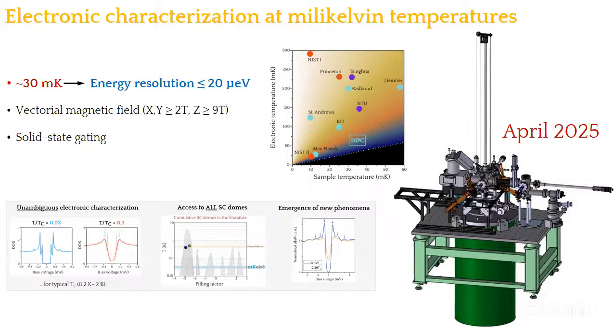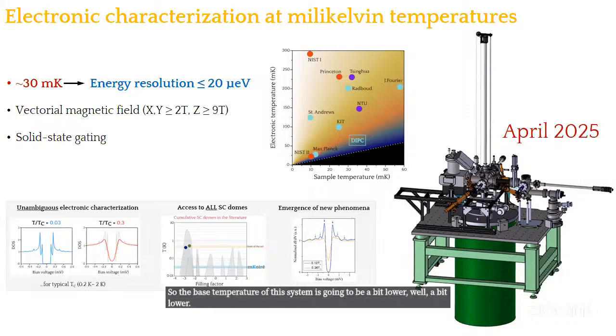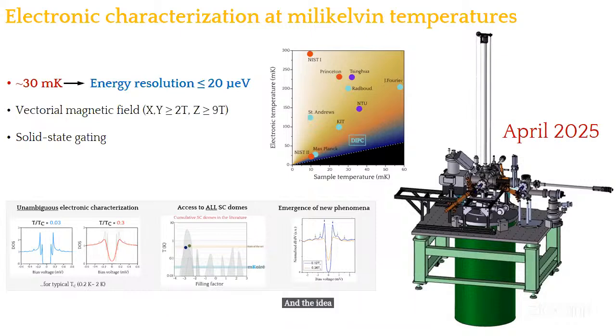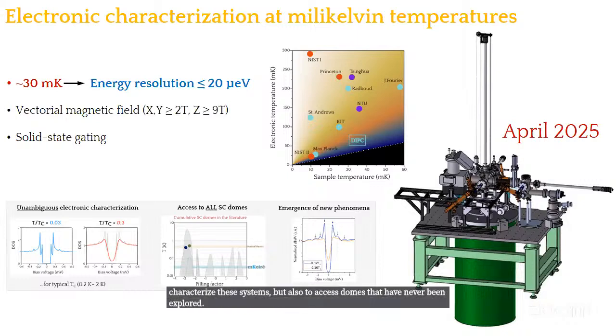The base temperature of this system is going to be quite lower than the one that we have. It's going to be a base temperature of 30 millikelvin. We expect to have energy resolutions around 20 microelectron volts. So we would like to live here somewhere. The idea behind it is not just to have a better resolution in order to unambiguously characterize these systems, but also to access domes that have never been explored. Or who knows, maybe there are new phenomena arising at these temperatures that nobody knows.